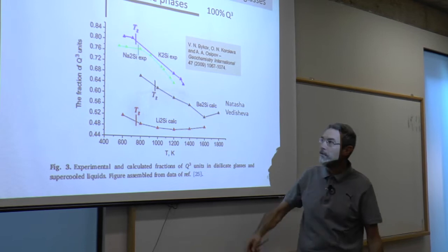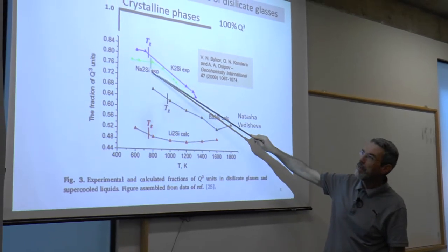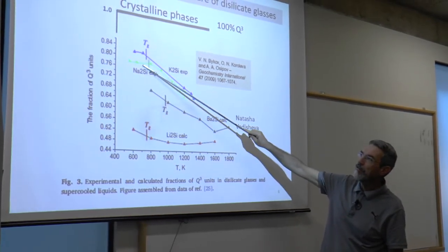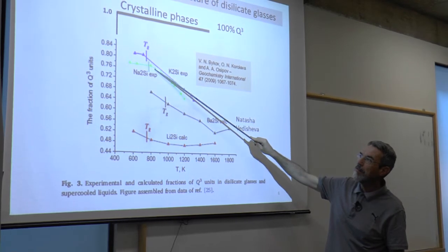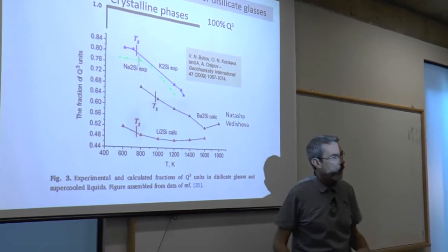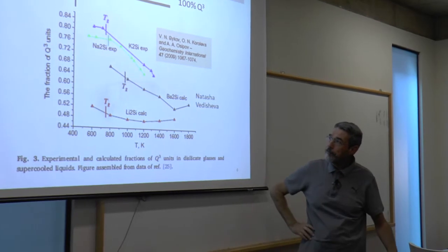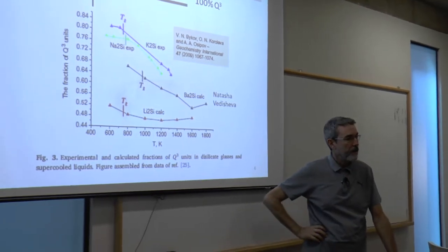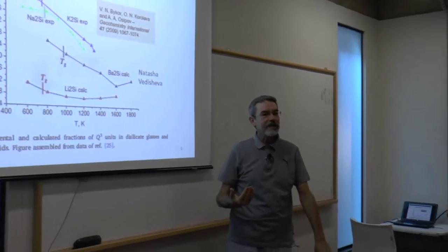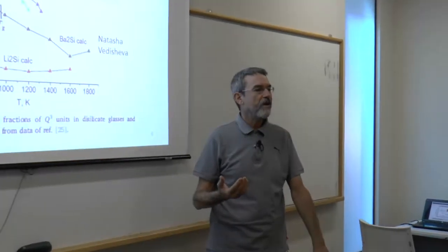And this is true for all materials. Look at the sodium disilicate. The structure of the glass is about the same as the structure of the supercooled liquid. So that's another indication that glasses are just frozen supercooled liquids. They have the same structure, basically. It's not like a solidification process.